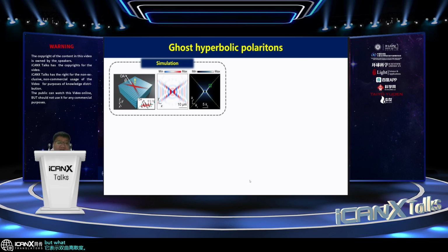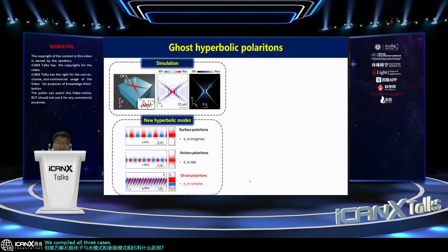But what is the difference of the ghost polariton compared with volume modes and surface modes? We compare all three cases here. For surface modes, the field is confined at the surface and is exponentially decaying into the bulk of calcite. It means that the wave vector along the direction perpendicular to the interface, Kz, is a purely imaginary value. But for the volume modes, it will propagate inside the bulk with a real-valued wave vector Kz.